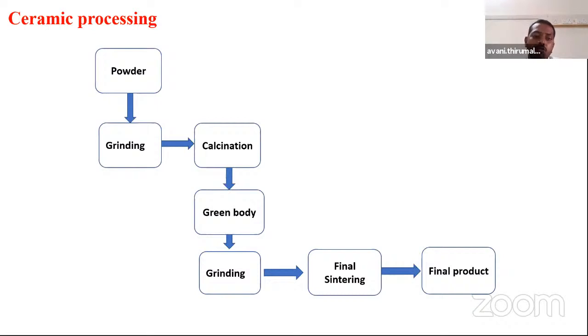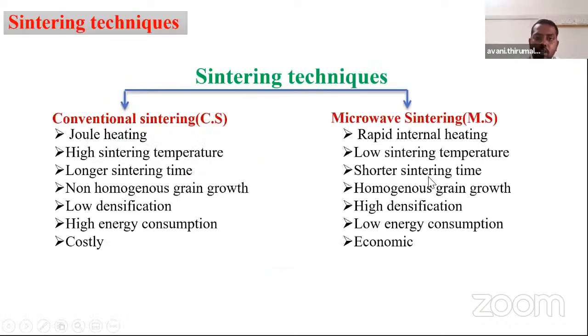Later, after grinding, we go for heat treatment, simply called calcination. After calcination, we can simply call it the green body. After the green body, again we grind it to reduce the particle size. Then we go to the final sintering, a heat treatment. Finally, we get the final product. I will give some differences between the conventional and microwave sintering techniques, how microwave sintering works, and how the lead volatility is decreased. We are avoiding the lead volatility in microwave sintering.